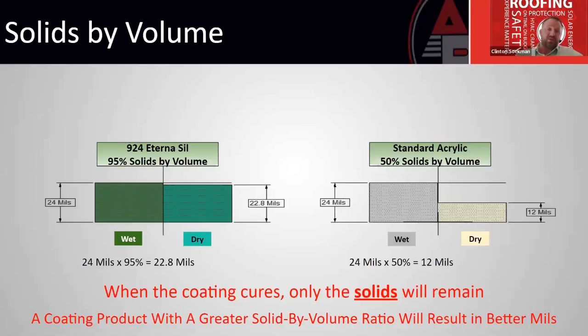In comparison to your standard acrylic, acrylics are 50% solids by volume, meaning there's an enormous amount of solvents, whether those are water-based solvents or petroleum-based solvents. That would yield from 24 mils down to 12 mils of dry thickness. So there's a significant difference in how much product is actually left on your roof after it's been applied, not just from silicone to acrylic, but from manufacturer to manufacturer.